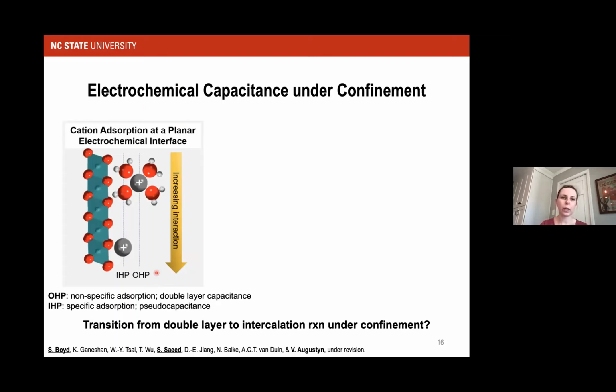We know fairly well what happens to the organization of ions at a planar electrochemical interface. For example, the distinction between non-specific adsorption versus specific adsorption. Ions in the outer Helmholtz plane retain their solvation and are undergoing simply an electrostatic attraction to the electrode without changing their local solvent organization, versus ions in the inner Helmholtz plane that are either fully or partially desolvated and are now chemically bonded to the surface. And this is where the idea of pseudocapacitance and double layer capacitance comes in. And the view in the field really has been that you have either process A or process B, that these are two very distinct phenomena.